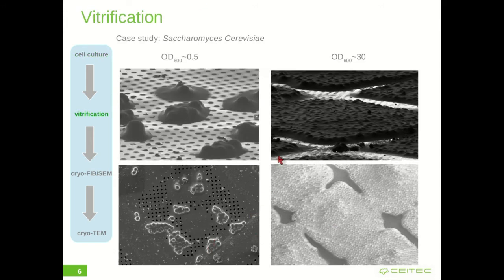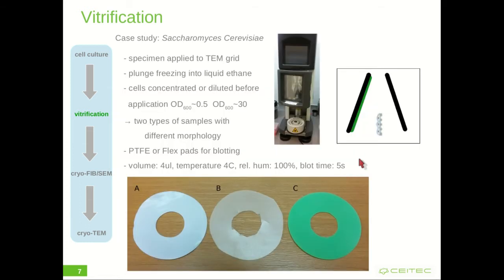In the case of Saccharomyces cerevisiae, for instance, the sample can either form small patches of the cells on the grid surface, or cover the whole grid squares with a monolayer of cells, based on the concentration of the cells that are applied to the TEM grid. In addition, the yeast has to be blotted against non-absorbent material in order to retain the cells on the grid. We have designed blotting pads which can be easily 3D printed from flex material, which is easier to access than, for instance, the PTFE pads, which are another option for non-absorbent blotting.